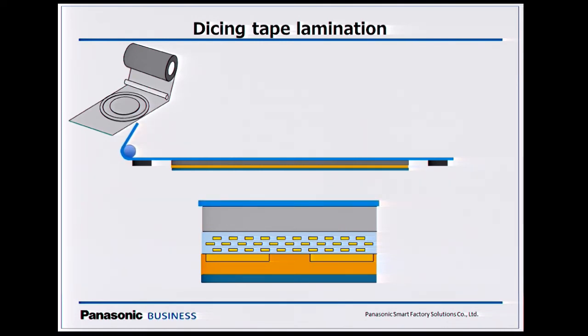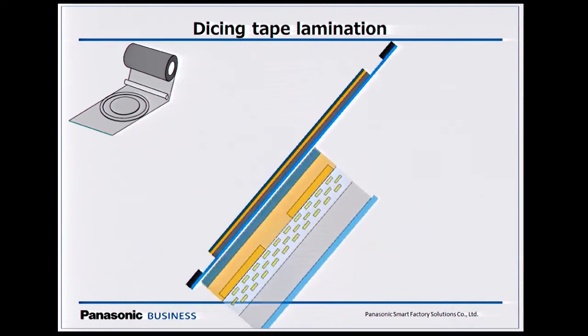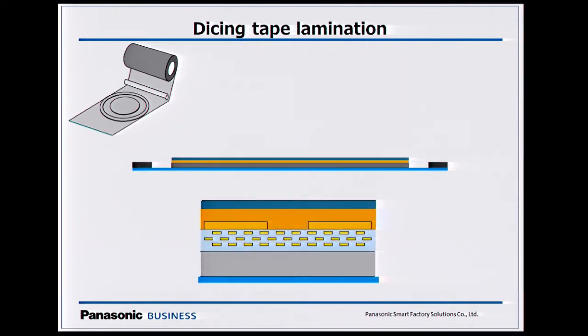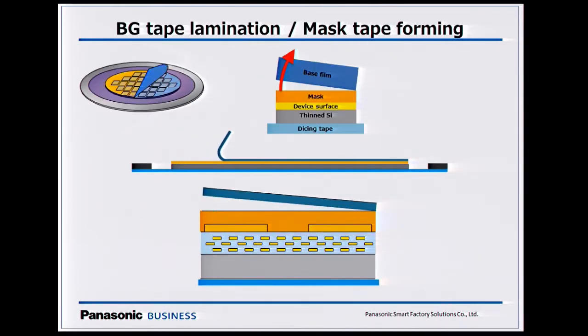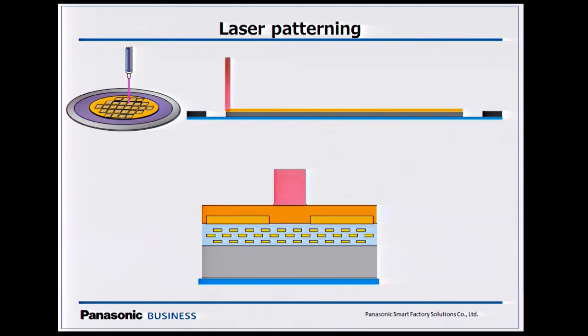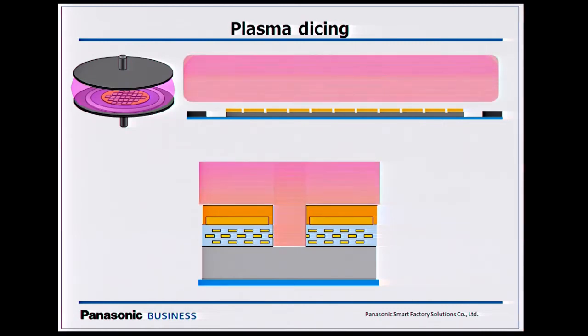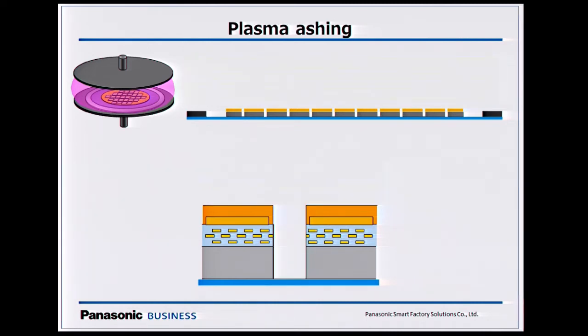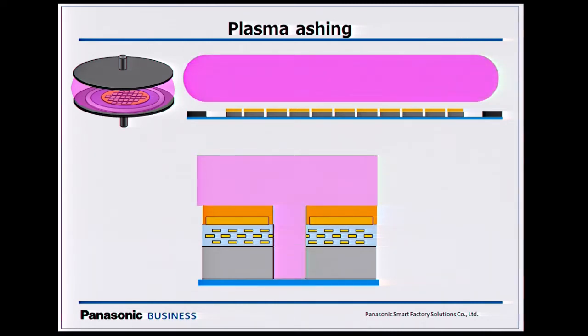Then we put that wafer onto conventional dicing frame and tape and remove the backgrinding tape, exposing this mask layer. That is then patterned with the laser, and then alternatively you can etch the metal, and then same as before, put it inside the plasma dicer, etch through the wafer until the dicing tape, and then ash off the mask.